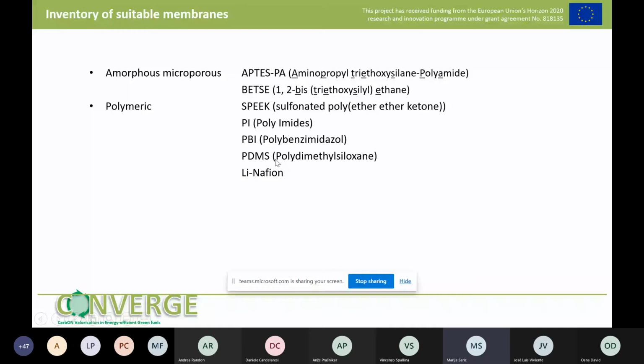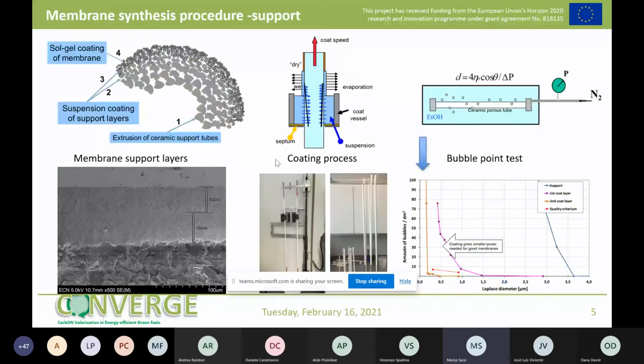Before I go into the test results and characterization of these membranes, I will just give a background of how we produce membranes at TNO. We produce supported membranes on tubular ceramic supports, and we usually buy these supports from a supplier. But these supports are quite coarse, so in order to make a good defect-free membrane layer, we need to apply intermediate layers to decrease these defects.